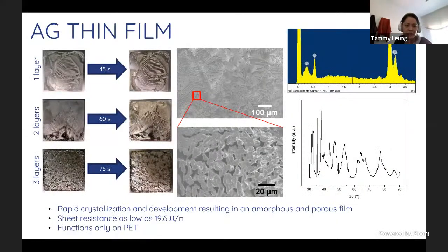The development of the silver film is very similar to the platinum films, where you can see very quick recrystallization of the ink, especially if a very thin layer was developed or printed, meaning that the crystallization pattern was completely seen and remained even during the conversion process.